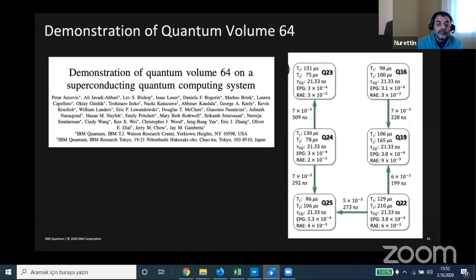Shown here are the gate errors and the coherence values. So you can see here the gate errors are very good, around 7e-3, 6e-3, 5e-3. Also, the gate time was tuned down to be around 300 nanoseconds to do this gate operation. And the T1 and T2 times, which are the decoherence times, so T1 was improved, and you can see here the range is 86 microseconds to around 130 microseconds, while T2 is around 78 or 75 microseconds to 210 microseconds.